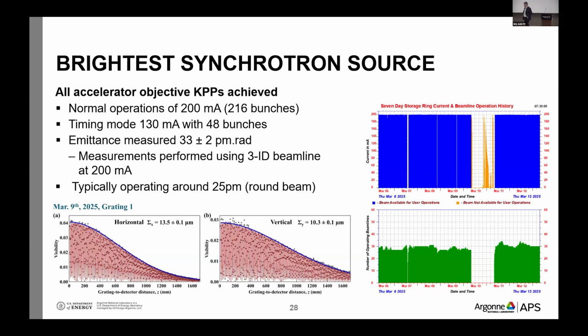But currently, Vadim told me recently that if you look at the average position of the gap of each undulator in the ring, we typically operate around 25 picometers emittance with round beam in conventional mode. So that's really exciting and really confirms that the machine works as expected.